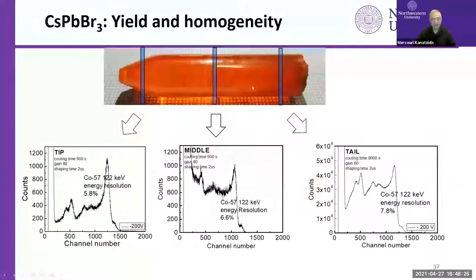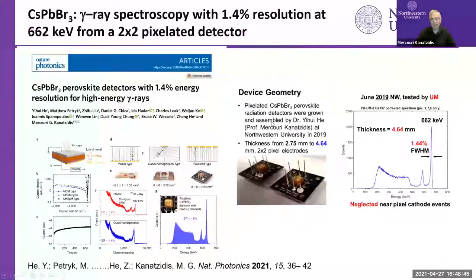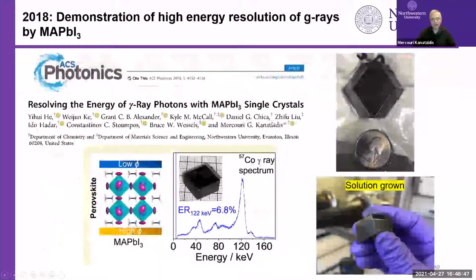I just want to make a point here. If this crystal was CZT, only a small part would be of great detector quality. The rest would not be as good and would have to be not used or discarded. Whereas here we think much more of the ingot, if not all of it, would be usable. And so that also drops the cost.